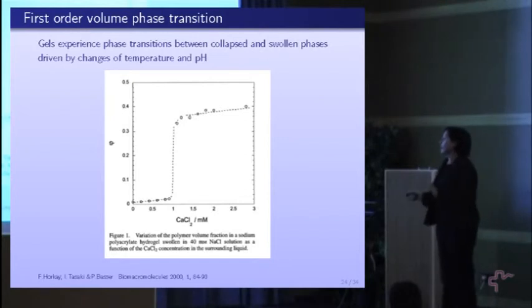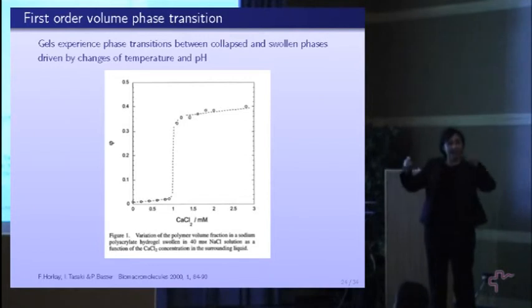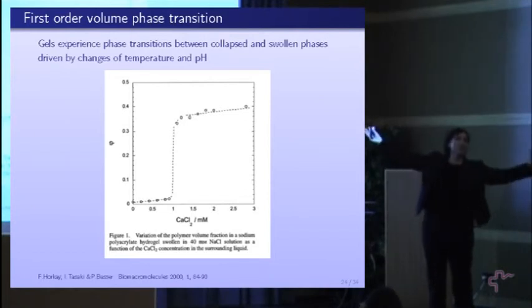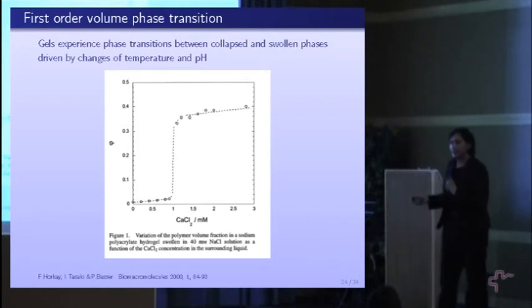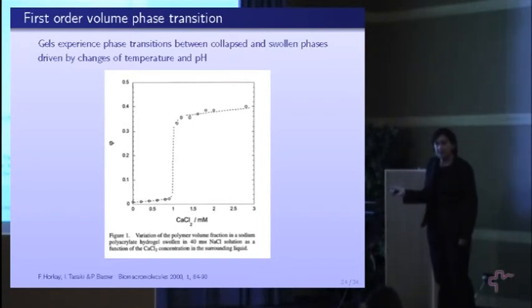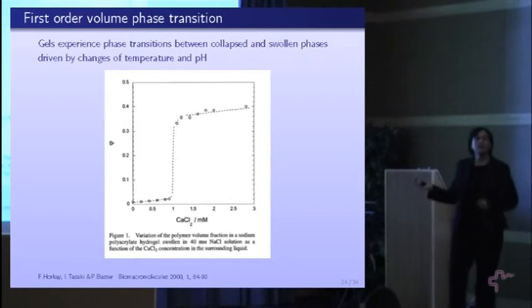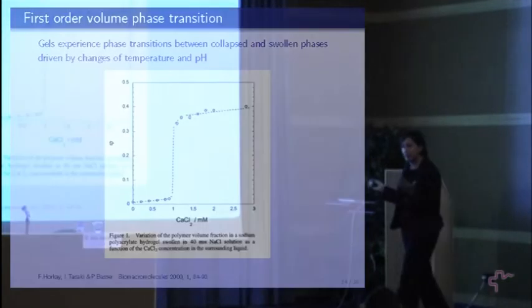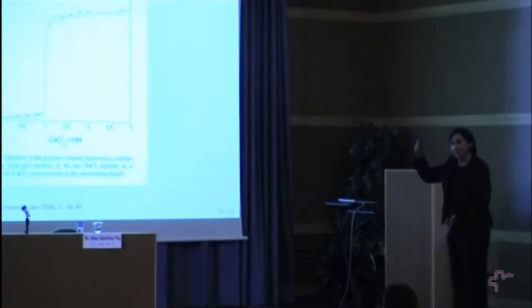And that's why, when we have enough of them neutralized, then there is no need for the elastic energy to be so big, for the system to pay so much elasticity, so then it can collapse. And in polyelectrolytes, this happens with a very, very big jump. And this is a relatively new phenomenon, so these kinds of polyelectrolyte gels are probably about 10 years old. They were known before, but really not the type that could give these huge changes.